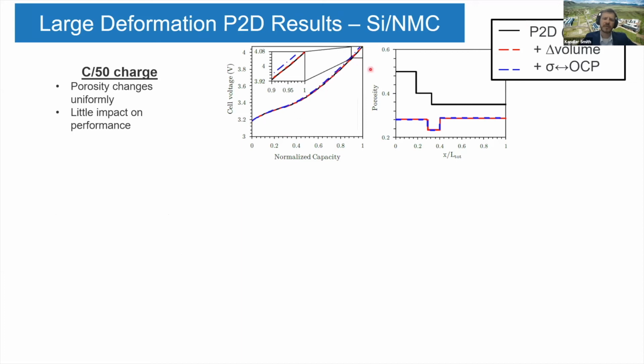But some things that you'll see, if you have a very slow charge, C/50 rate, here all three cases show up similarly. What we've got is in black is the traditional P2D model with no volume expansion. And so the porosity of these three different regions stays uniform between the beginning and end of discharge. And so this is essentially what we've initialized the model to for, I believe this is the anode, the separator region, and the cathode. And for these other two cases, there's a really uniform expansion of the silicon anode that reduces the porosity, which was initially 50% down to just about 30% or a little bit less. And the expansion here, I believe these are fixed boundary conditions. The expansion is taken up by the separator as well as the cathode. So those have to compress as the silicon anode expands.